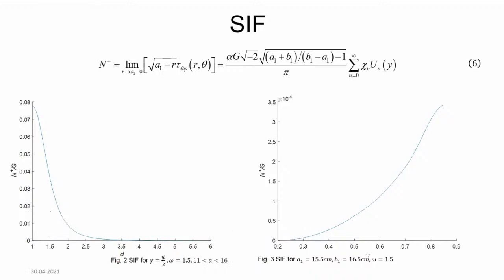Here, for example, we move the crack of the same size in the middle of the angular coordinate theta from the bottom spherical face of the cone to the middle, and we see that when it's close to the spherical face, the stress intensity factor is higher. Here it is the same when we move the crack to the lateral surface of the cone. We can see here that it is higher when we approach the border. So also we can see that the overall values of the stress intensity factor are higher when we cross the border on which we apply the stress.